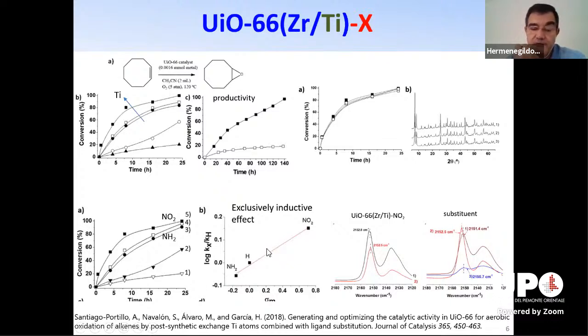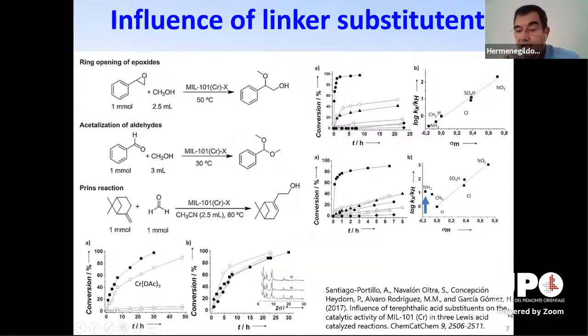And if you plot the Hammett sigma constant, which is a measure of the electronegativity of the aromatic ring, against the relative initial reaction rate, what you obtain is a linear plot. This means that in this case, for this particular reaction, what we are monitoring is just acidity without any other role from the substituent that we have introduced, because we have a linear plot. However, in other cases, like the one I'm going to comment on now, we observe a deviation from the linearity of the Hammett sigma constant. So this indicates that this substituent is playing a role per se. So here, really a bifunctional catalyst.